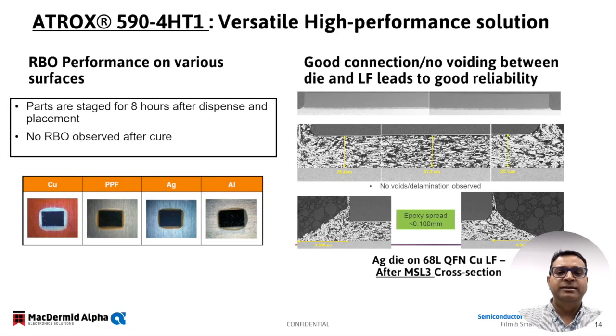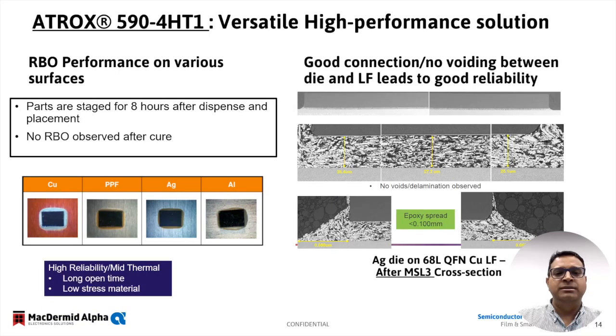On the right hand side here are some SEM cross-section images that show good connection with the die as well as lead frame surfaces, but also good compatibility with the molding components you can see on the bottom right image. These cross-sections have been taken after MSL exposure, showing the robust adhesion performance that leads to good reliability with this product. This product also has desirable attributes like long open time, which provides a wide process window in a production environment, as well as low stress in cure state.